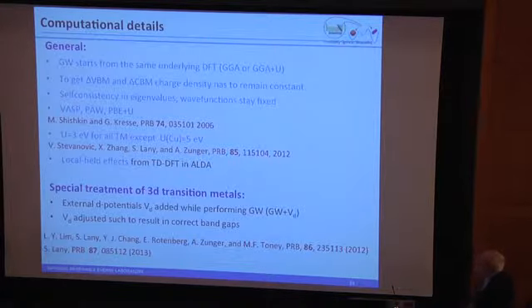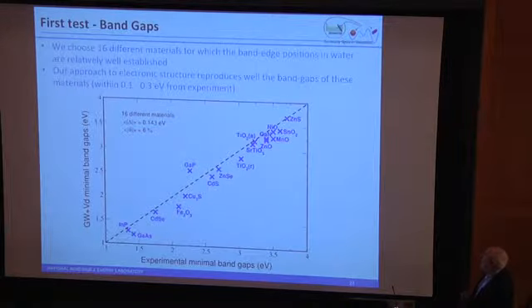Okay. So there's some more details here about how we actually do it. So GW starts from the same underlying DFT using GGA plus U. We'll talk a little bit more about that later. The charge density has to remain basically constant, and there's got to be self-consistency. And we look at local field effects. There is a little bit of a special treatment for 3D transition elements. You have to put in the external D potentials, and Vlad can explain that much better than I.